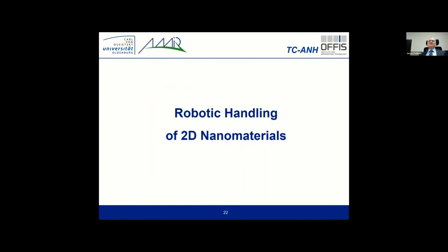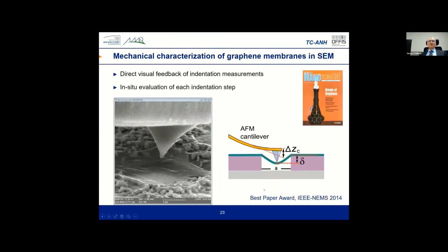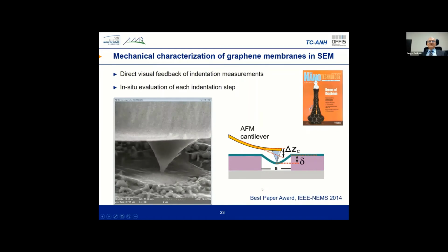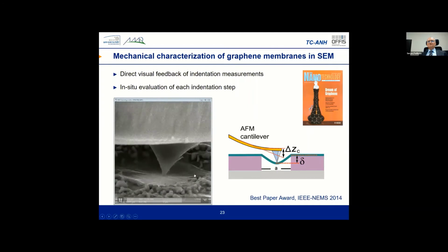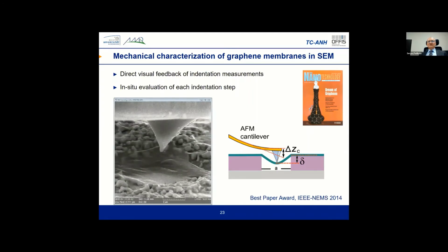The second piece of activities that I want to present to you is robotic handling of 2D materials. In early work here, the first time we implemented the mechanical characterization of a graphene membrane. This membrane is less than 2 nanometers thick, and it was a really interesting result at the time. It was 6 years ago now. The technology is simple actually, yeah? Everybody knows this characterization and calculation of Young's modulus if you can follow the deflection of the membrane and measure the force of the indentation, but try to do this at nanoscale.